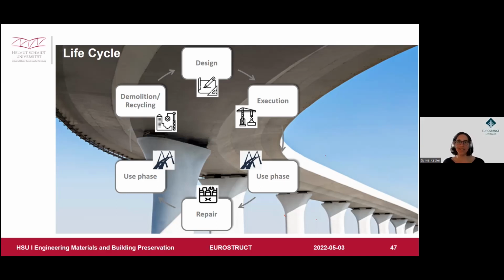Every piece of information assists to give a full view on the corrosion assessment of your structure. It's totally right. The half-cell potential measurement is dependent on the moisture condition of the concrete, but since we evaluate the results qualitatively relative to each other, we need to ensure only that we compare those parts of the concrete which are in an equal moisture condition. If we have different moisture conditions on a structure, which could easily happen if some part is directly exposed to rain and the other not, we should not put all the potential data in one database and evaluate them. We need to divide the structure by moisture condition, measure the half-cell potential, and make the evaluation depending on the moisture condition. And as soon as you additionally have the corrosion rate measurements together with your half-cell potential, this would decrease the uncertainty of your corrosion statement.